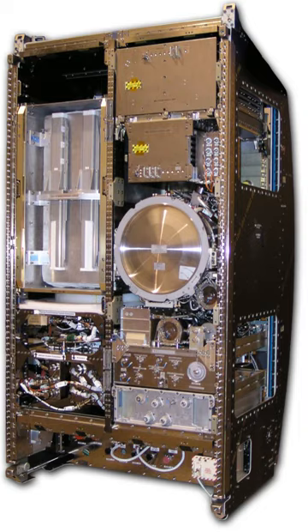The core facility supports FIS with up to 8 heating elements, and provides the mechanical, thermal and electrical infrastructure necessary to handle the FIS, the sample cartridge assembly (SCA), together with any associated experiment-dedicated electronics that may be required. A FIS is an arrangement of heating elements, isolating zones and cooling zones contained in a thermal insulation assembly. On the outer envelope of this assembly is a water-cooled metal jacket forming the mechanical interface to the core facility.